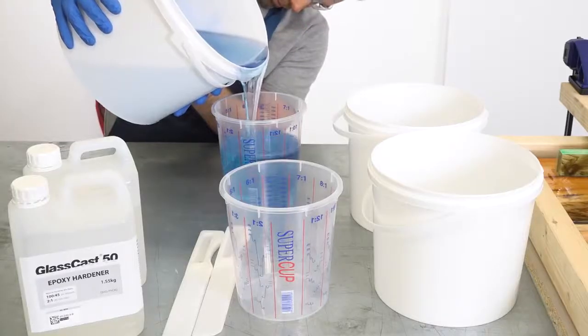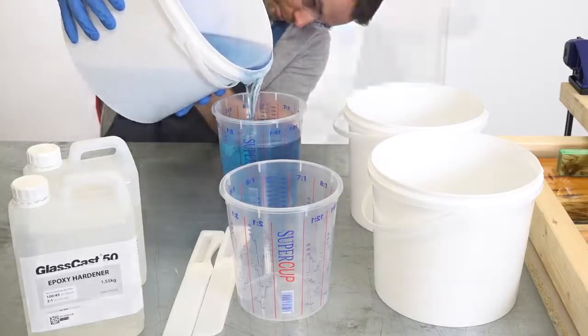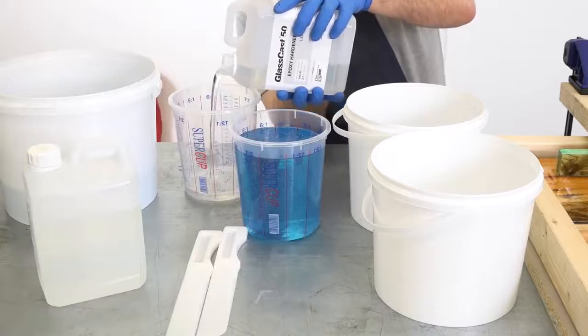Because the depth of our table is 40 millimetres, I'm actually going to split the main pour into two separate stages, allowing the resin to cure to its B stage between each pour. This will avoid the risk of the resin overheating whilst it cures, which is a problem that we could face if we tried to do the main pour all in one go.